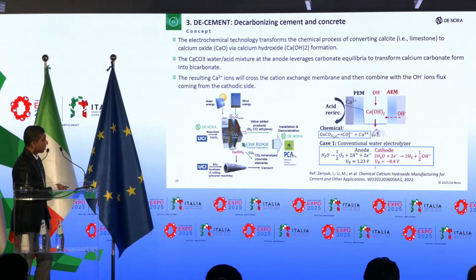So what we are planning on doing here, we're starting with the calcium carbonate. We can put it in some kind of acidic environment on the anode side of this reactor. And through the proton exchange membrane, we can pull the calcium into the middle compartment. And from the cathode side, we can obtain hydroxyl ions and precipitate this calcium hydroxide.